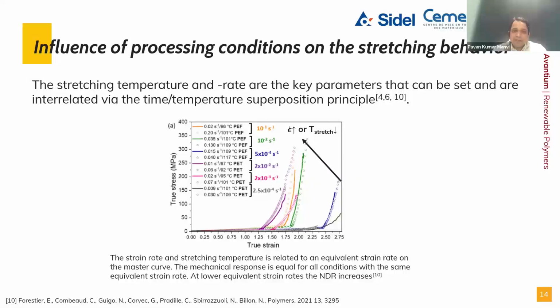So if we see the impact of the temperature and the impact of the shear, then we can see how the polymer is behaving. In the previous slides, we learned that the reptation time of the PEF is much shorter. That means if the temperature is applied, then definitely due to the reptation behavior, the strain will increase. And if the shear is applied, due to the lower reptation time, a faster orientation can be achieved. And due to this faster orientation, the strain hardening starts.